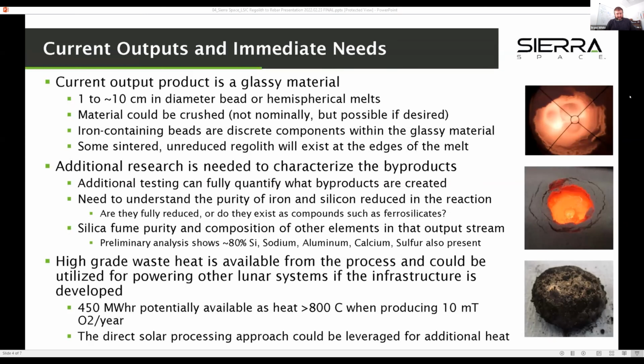So we've done some testing, but the analytical testing we have done always assumes that the materials they identify are in their common oxide state, and you'd want to do some testing to better understand what's truly there, not just the oxides you get from the testing. So are they fully reduced or partially reduced? Does the iron exist as a ferrosilicate or what?